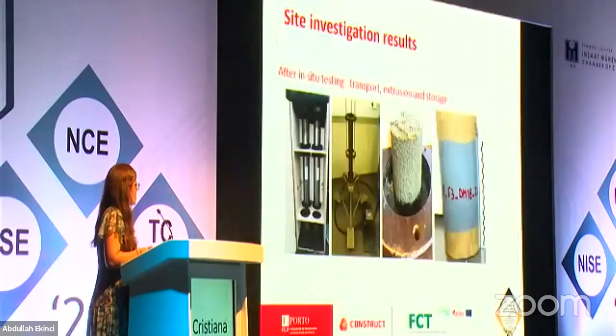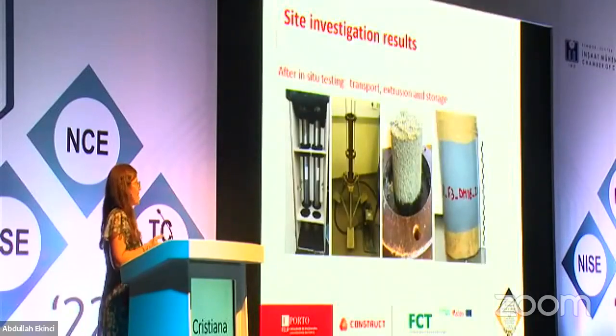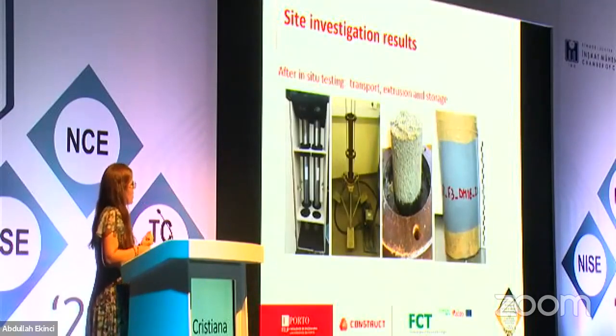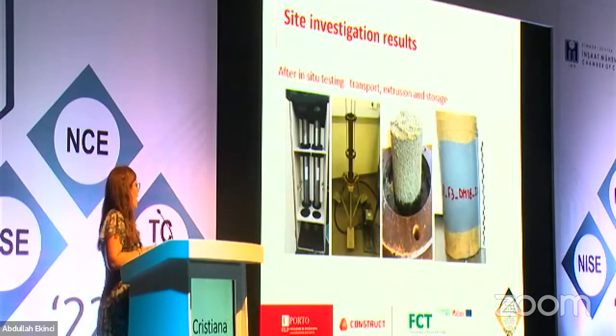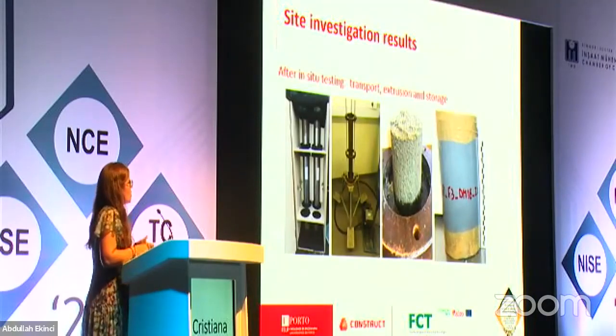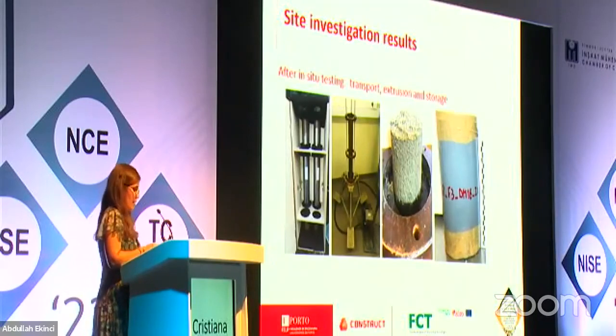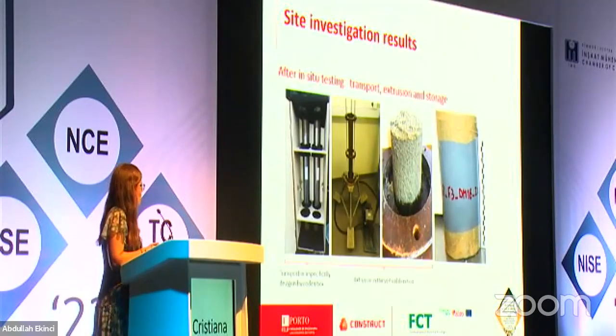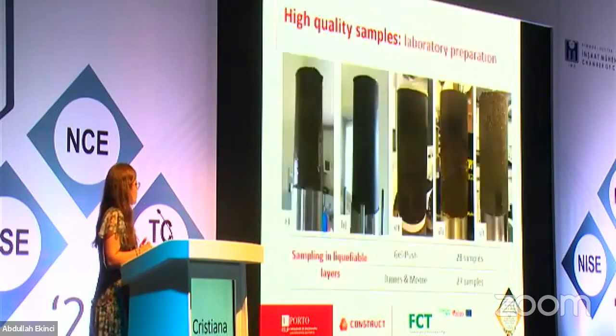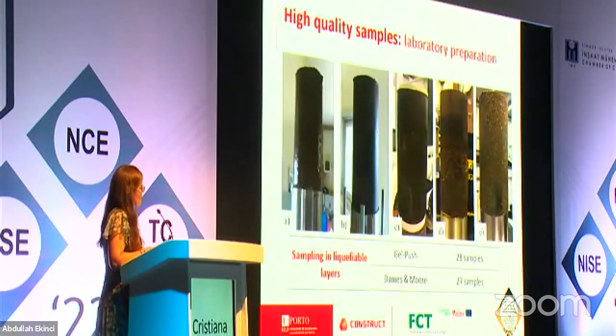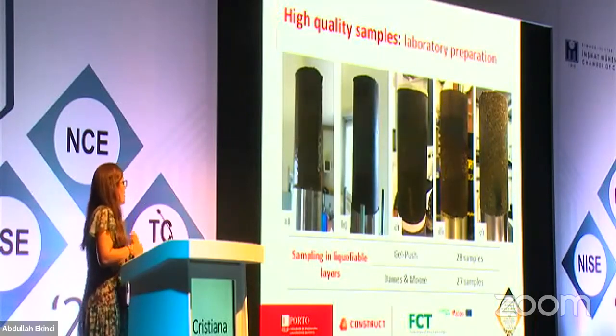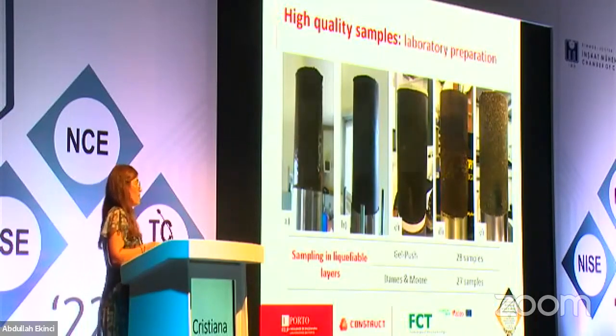And you can see here an example of a collected sample that looks very sandy. And after this extrusion, which was executed immediately after sampling, we stored the samples in PVC liners to make sure that they were kept in temperature and humidity control conditions, and they were sealed to avoid any water content transfer. And you can see here different examples of the collected samples. Some you can see they look more clayey and others look more sandy. That's the very little bit that we got.